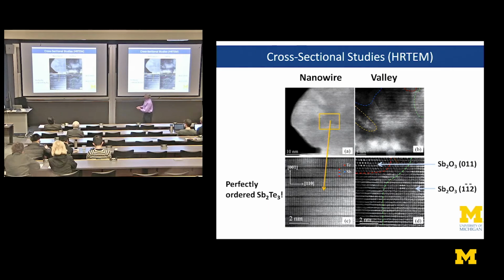So what's really interesting is that within the wire region, there's a perfectly ordered antimony telluride, just like it was when we grew the film. So this part of it is undisturbed, with perfectly ordered quintuple layers, as you would expect. Between the wires in the valley, and this is where we saw the oxygen, it's not anywhere near as nice. It's highly disrupted into grains with these dashed lines here indicating individual grains. And the zoom in on that shows us that we have different orientations, whereas this was perfectly ordered.